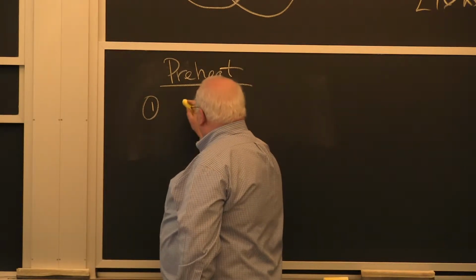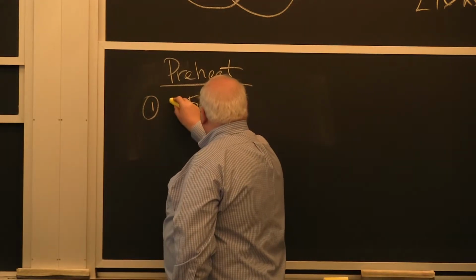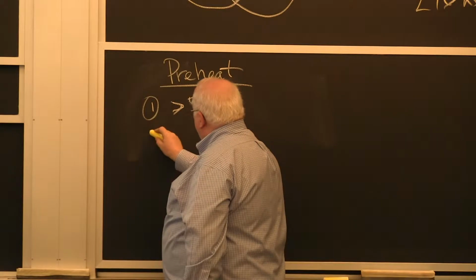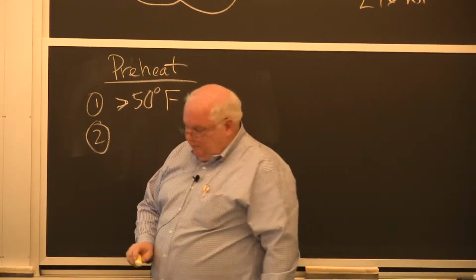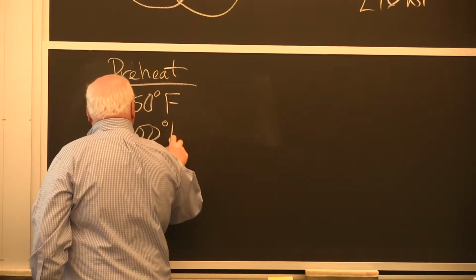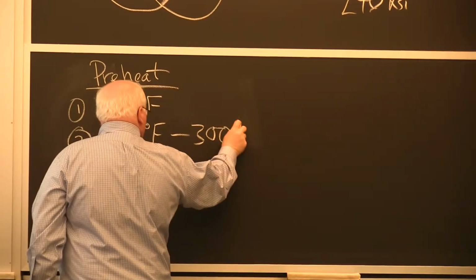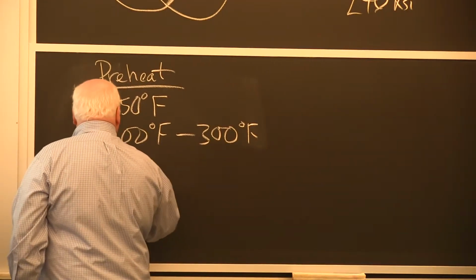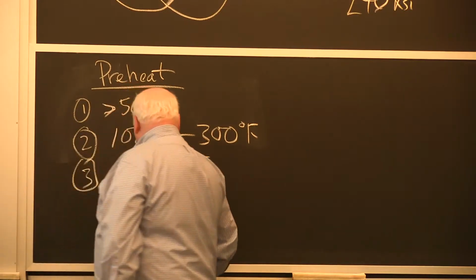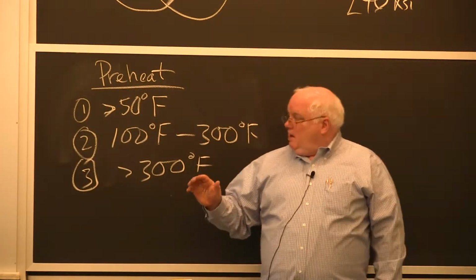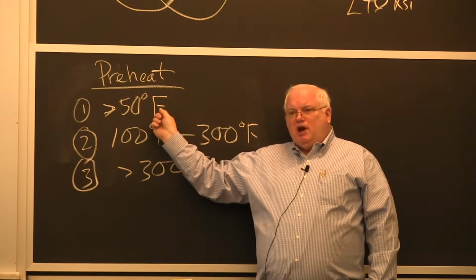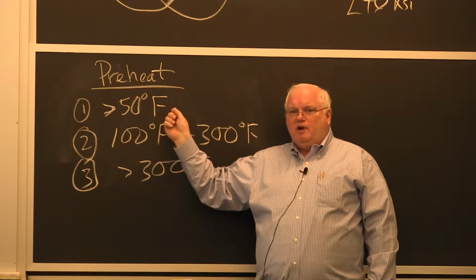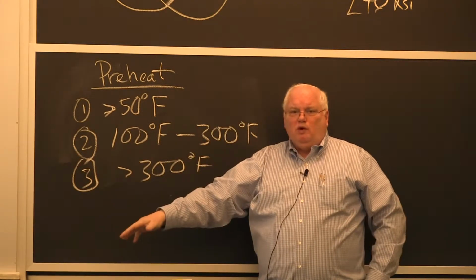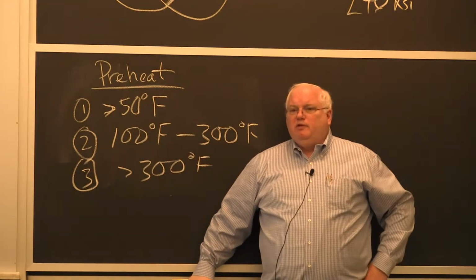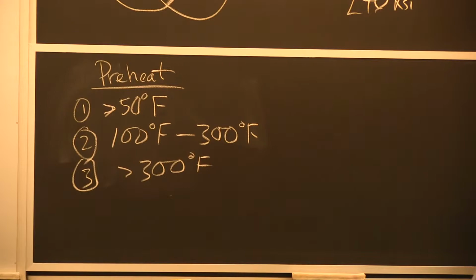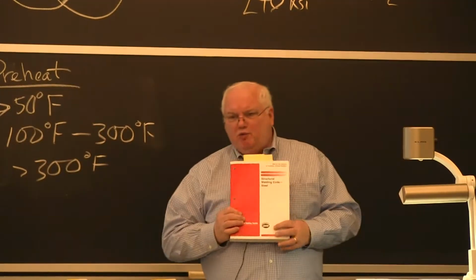So there's 3 levels of preheat. One is 50 degrees, must be greater than 50 degrees Fahrenheit. One is you heat the steel from, let's say, 100 degrees Fahrenheit to 300 degrees Fahrenheit. And the third level is greater than 300 degrees Fahrenheit. Well, what are we doing with each one of these? The ASME boiler and pressure vessel code says you shall not weld on steel if it's below 50 degrees Fahrenheit. I don't care if it's the mildest steel in the world, you don't weld if it's less than 50 degrees Fahrenheit. The structural welding code, which is probably this, well, these 2 codes, ASME boiler and pressure vessel code.